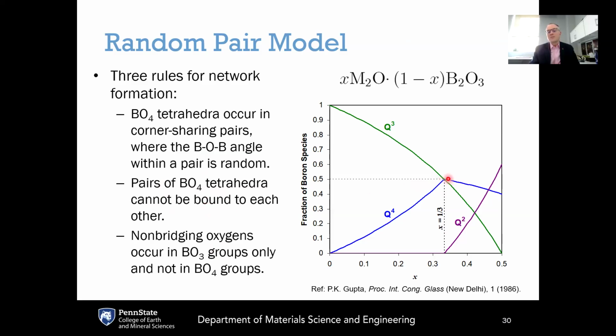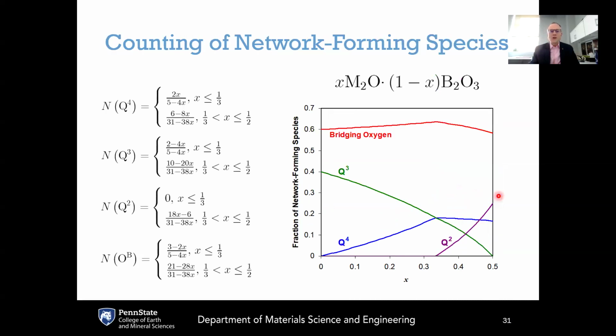And what this means is that beyond this point, at X greater than 1/3, we are forced to form Q2 units. We're forced to form non-bridging oxygens. And because of having fewer bonds available, because of the non-bridging oxygens, the population of tetrahedral units also decreases. So we can use this then to give us these equations here that show the evolution of the three different types of boron units here, Q2, Q3, Q4, and also account for the number of bridging oxygens here.